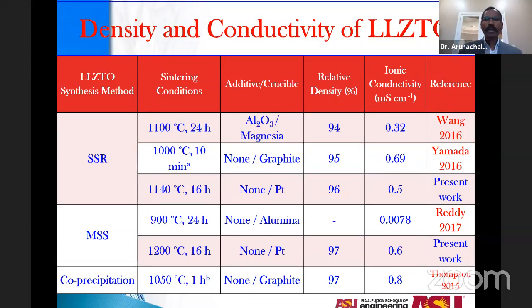So, with the multiple densification process in garnet electrolyte, I think in 2016, Yamada et al. reported 0.69, but we could get only up to 0.5 by the solid state reaction, and also around 0.6 with the molten salt. And there are also different methods with co-precipitation. That one actually showed the highest conductivity as of now.